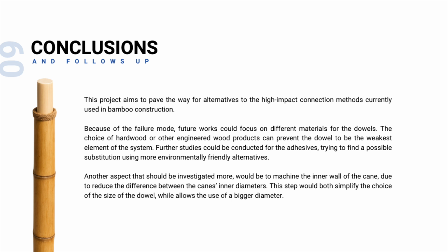Also, another potential improvement would be to machine the inner wall of the bamboo culm, because at the moment the inner diameters vary significantly from one to another. And this variability complicates the selection of dowel sizes. While by machining the inner surface, we could reduce this variability, which would simplify the design and allow us to use larger dowels, for example. And this could lead to a stronger joint and a more standardized process overall.